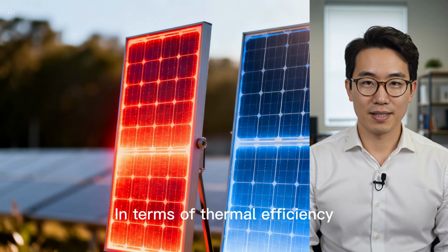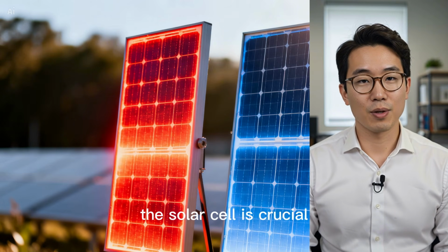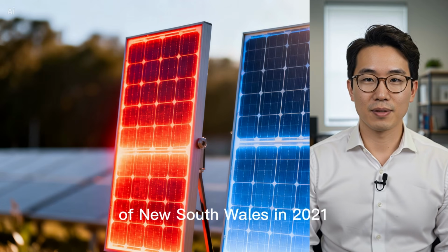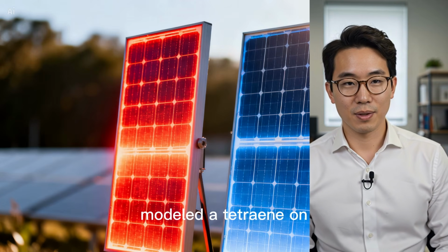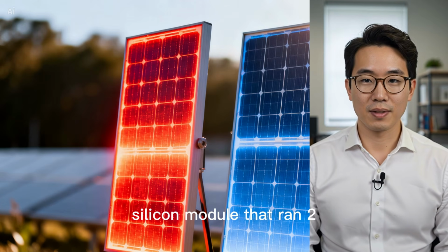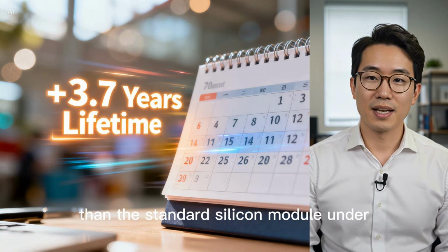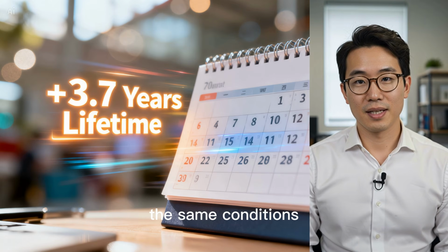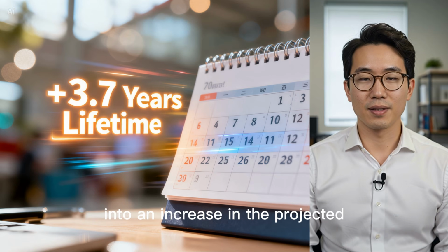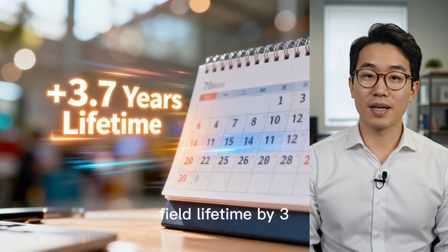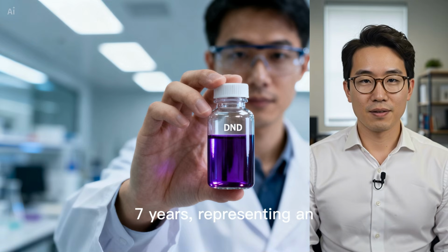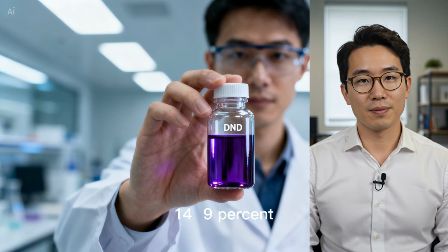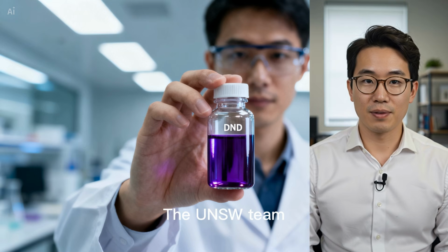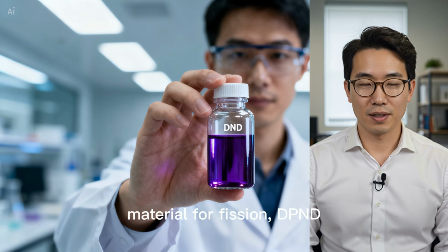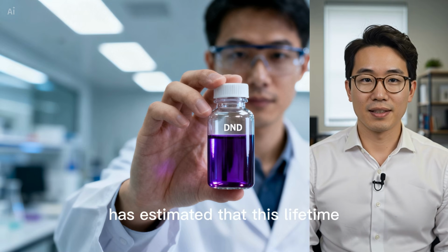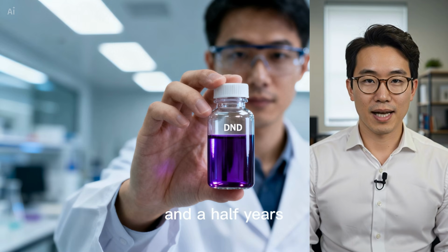In terms of thermal efficiency, reducing heat inside the solar cell is crucial. A team at the University of New South Wales in 2021 modeled a tetracene on silicon module that ran 4 degrees Celsius cooler than the standard silicon module under the same conditions. This modest temperature reduction translated into an increase in the projected field lifetime by 3.7 years, representing an improvement of 9%. The UNSW team, working with a more stable material for fission, DND, has estimated that this lifetime extension could go up to 4.5 years.